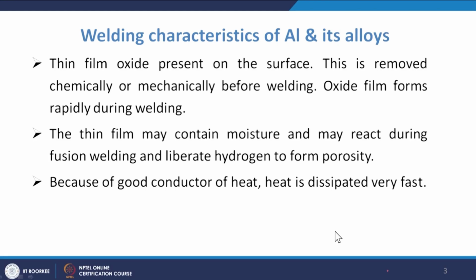When coming to the welding of aluminum and its alloys, the thin oxide film present on the surface is removed chemically and mechanically before welding. The oxide film forms rapidly during welding. The thin film may contain moisture, which may react during fusion welding and liberate hydrogen to form porosity. Because of the good conduction, heat dissipation is very fast.